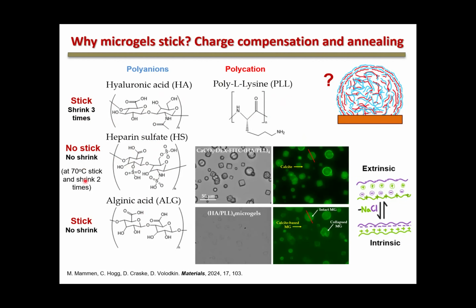Other 2, so they stick to the surface. If you go to alginic acid, it sticks to the surface but does not shrink. If you go to the heparin sulfate and polylysine combination, it does not stick to the surface and does not shrink, unless you heat up the system a bit, then it starts to stick and shrink about 2 times. So there is still a kind of mystery there, but some polymers which look very similar, biopolymers, give with the same polycation either sticky or non-sticky particles, so we can see black and white if you want.